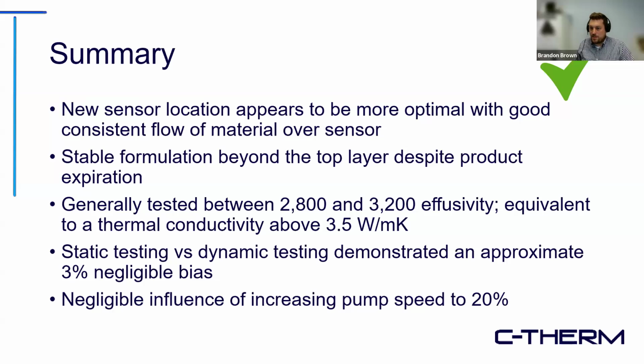We also tested to see if the material moving across the sensor had any effect. This was basically to show that static testing with the pump stopped versus dynamic testing with the pump running demonstrated a negligible 3% bias during normal operation, and even increasing the pump speed to 20%, which I believe was the maximum nominal operating speed for some of this equipment, only showed a further 1% bias in the results.